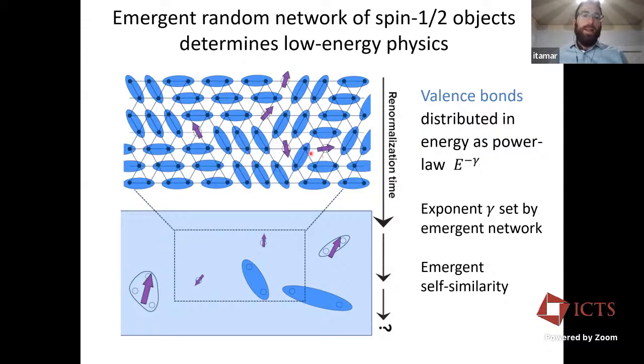For example, if I just put spins randomly in space and try to do strong disorder RG, then I assume some distribution. The distribution is a log normal distribution, which isn't a power law. At low energy the tail looks like a power law, but exactly what the power is can change. And that's even just the starting point. Actually, when people do strong disorder RG, it's kind of unknown what you get. I was brushing over that point, but in strong disorder RG you get some of these singlets, but you also get triplets. And when you get triplets, maybe this even leads to some spin freezing at some very, very ultra low temperature.